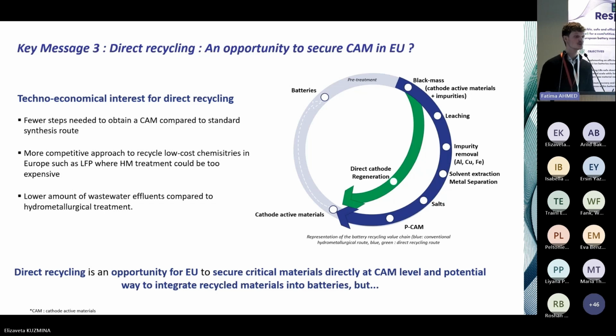If we have less process steps, we could also imagine to have lower cost with direct recycling approach. And if we have lower costs, it could be also a way for Europe to have solution to recycle low-cost chemistries such as LFP, where current hydrometallurgical treatment technologies will have some challenges to propose a competitive solution. Last point, also quite critical for hydrometallurgical treatment, is the amount of wastewater generated. With direct recycling and process less intensive in water, we could have also a decrease of the amount of wastewater needed for the process.